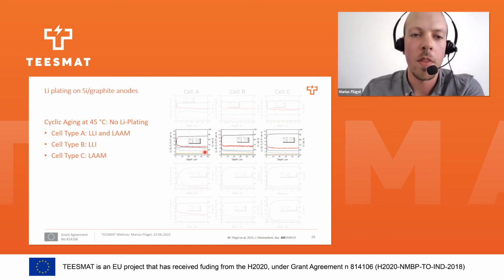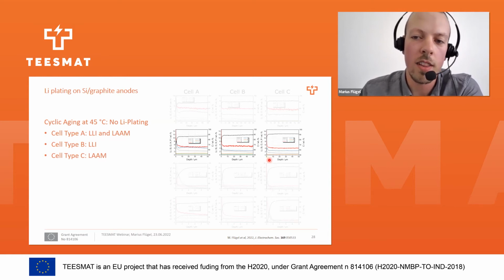For cell type A and B, we saw a high amount of lithium, which was due to the loss of lithium inventory, which was obviously trapped in the anode. For cell type C, we didn't see a sharp increase of lithium in the anode, which is also conclusive with the fact that we observed loss of active material.